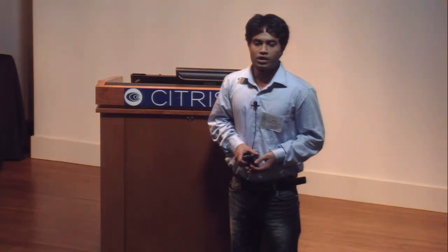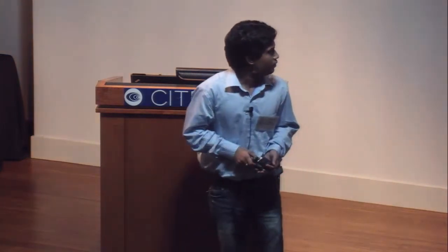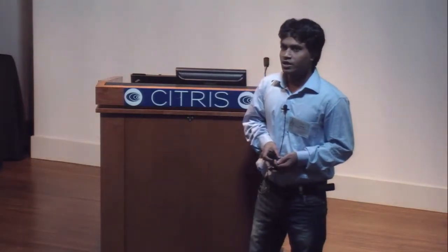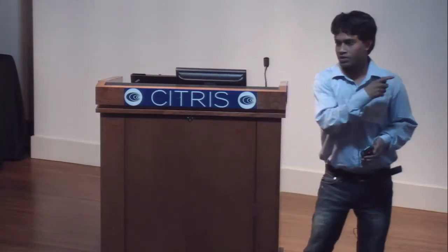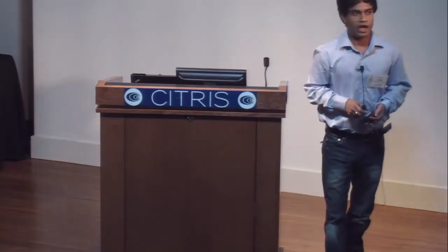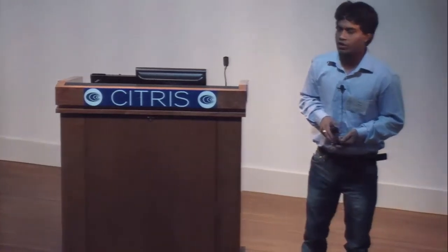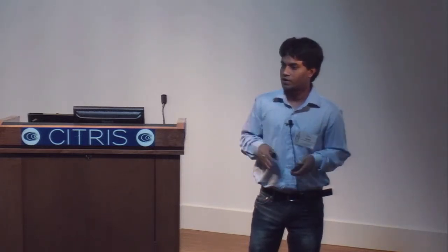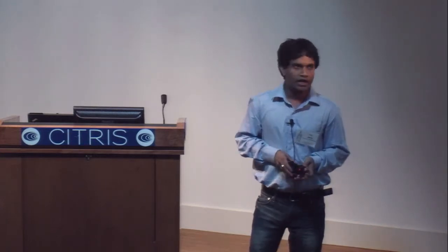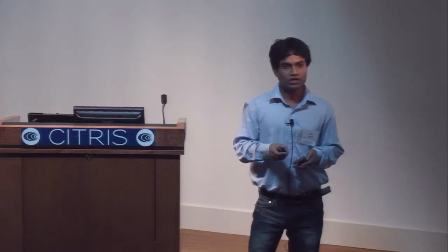In simulation, I did not include the hysteresis, but I believe in negative capacitance there should be some sort of hysteresis once this system bifurcates on the charge states. But I believe there is also an experiment going on at Intel, and they are going to present it this year at IEDM, this piezoelectric gate barrier, and they have clearly seen the 40 millivolt per decade sub-threshold slope. How much was that? 40 millivolt per decade. They've seen 40 millivolt per decade, yeah, but they have also seen the hysteresis is kind of 200 millivolt. I mean this dual scan, the hysteresis, yeah.